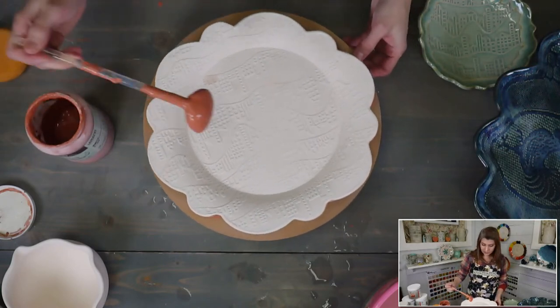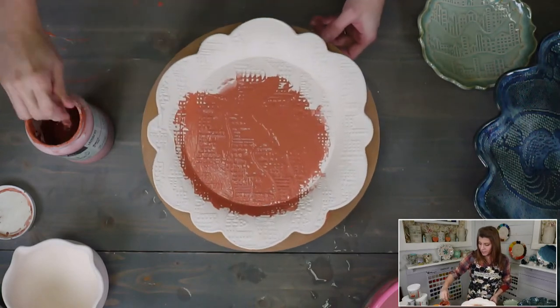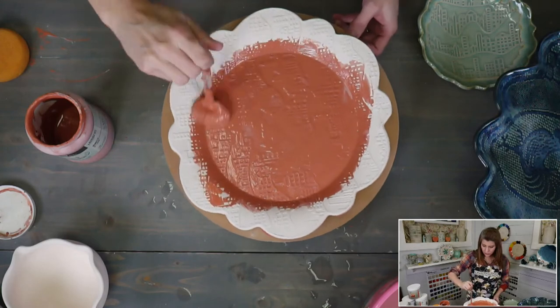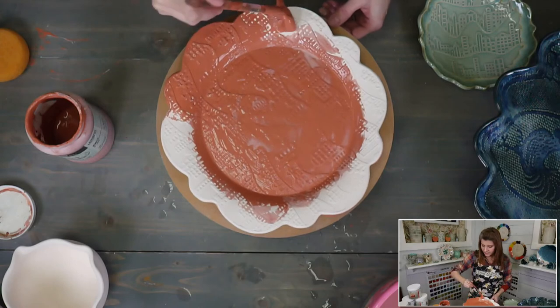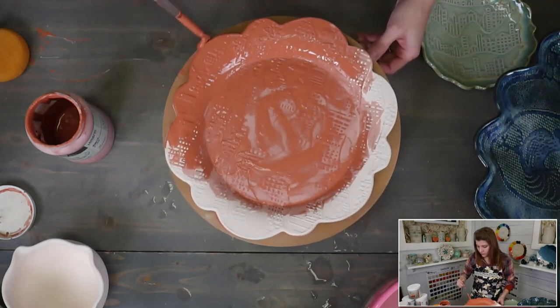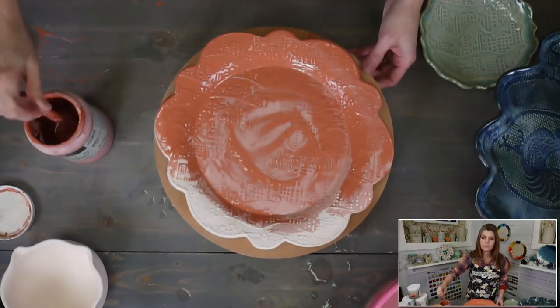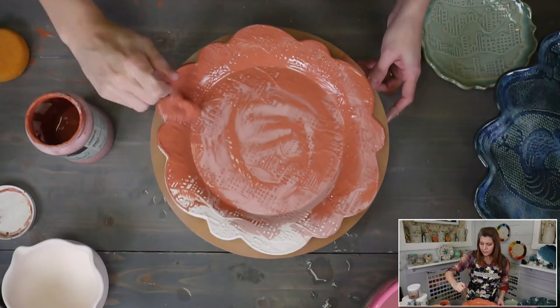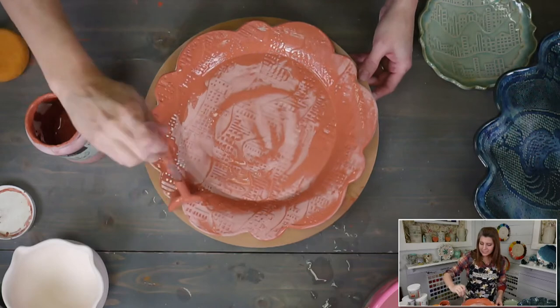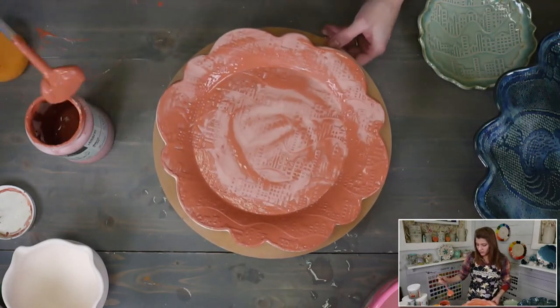Although this glaze looks really dark right now, it's going to turn into a beautiful light transparent green-blue color. The red you're seeing is actually iron oxide in the glaze. Highly concentrated iron oxide can be brown or black. Spanish red iron oxide gives colors ranging from rusty brown and tomato red to deep black-brown. At lower concentrations you move down to olive greens, then light celadon green, and then to the aqua we have here.